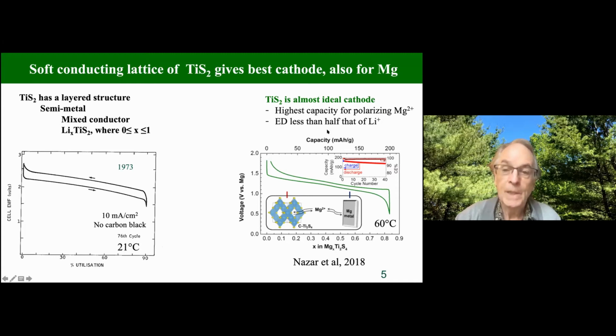The really big issue with magnesium, you can see the voltage at half discharge is about 1.2, 1.3, compared with about 2 to 2.1 for lithium. So magnesium suffers from about a 1 volt deficit, which I think is not going to really allow it to be used in commercial systems. Calcium will be more promising, and being a larger cation, it might diffuse better.